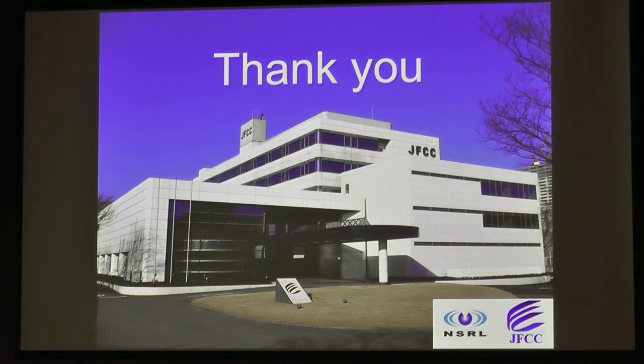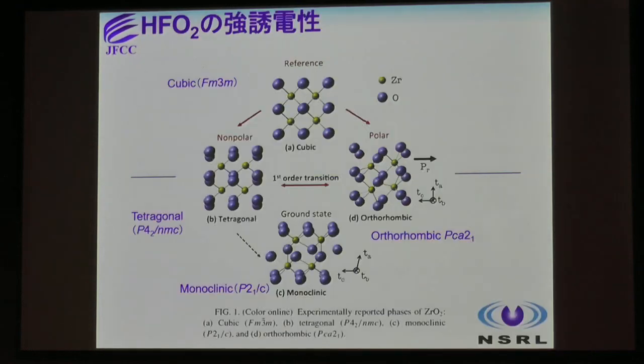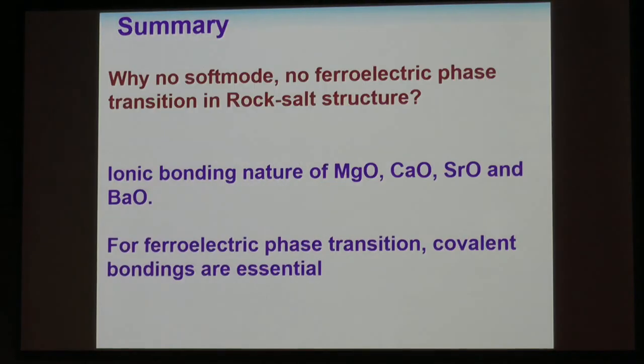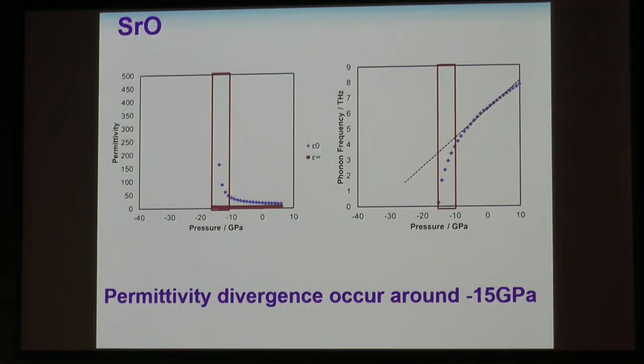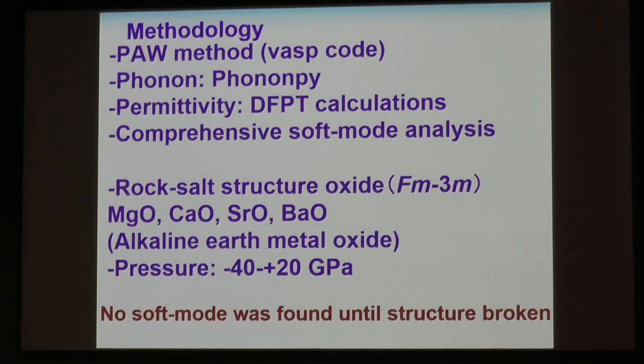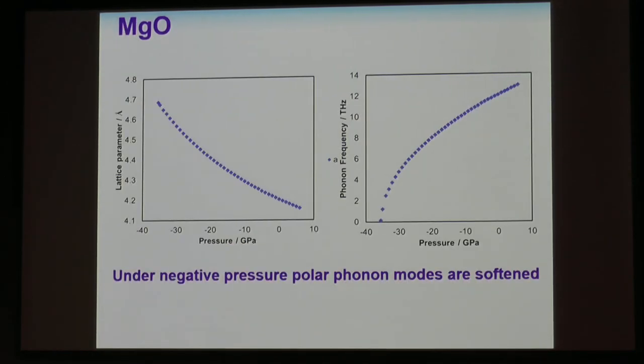I have a question about your breakdown. You enter the coordinates in the rock salt structure, and then you compute with a very large lattice constant, as I understand. And then what does it mean, breaks down? Does it dimerize or what? I imagine you can go very, very large. What do you mean by breakdown? How does the calculation breakdown come out? No bonding, maybe. But you have a cell with 2 atoms per cell. You can compute with a lattice constant of 1 meter and get the result. Here, only 10% expansion. Yeah, but this is the breakdown ratio as shown here.